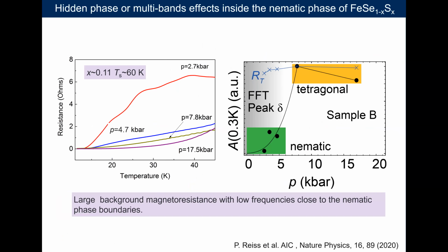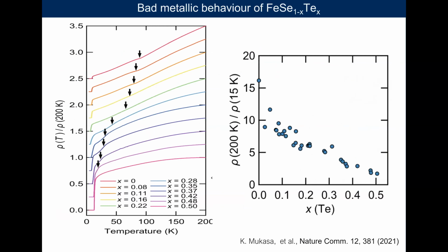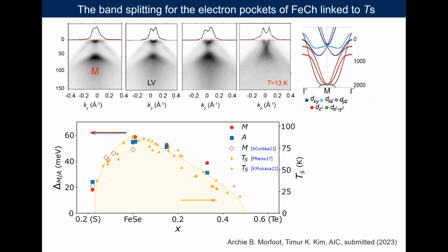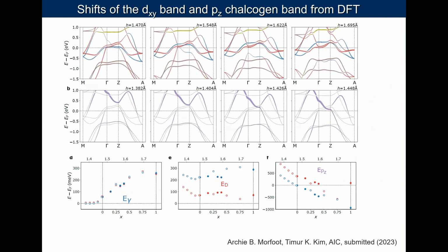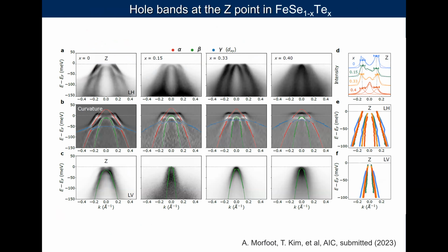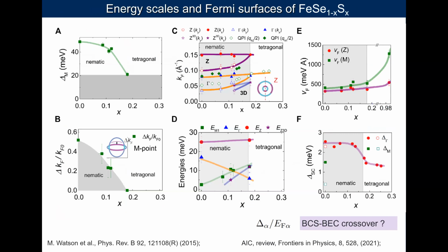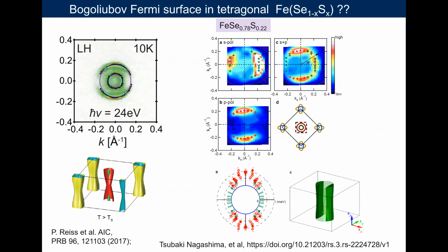Okay, so there are two issues. In principle, you have the information about the anisotropy of the spin fluctuations, right? And you also have some information about the gap anisotropy. So yes, the gap anisotropy has been measured both by STM and ARPES data, and they show indeed very strongly anisotropic behavior. Yes, and does it relate with the anisotropy of the spin fluctuations?